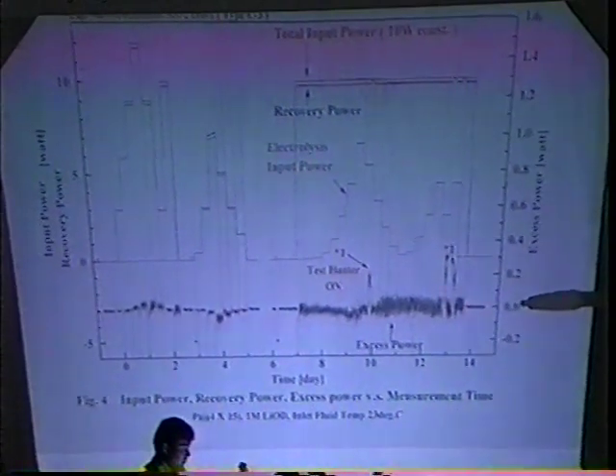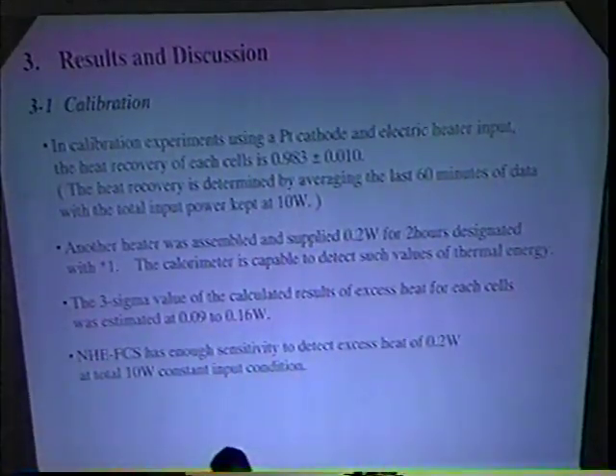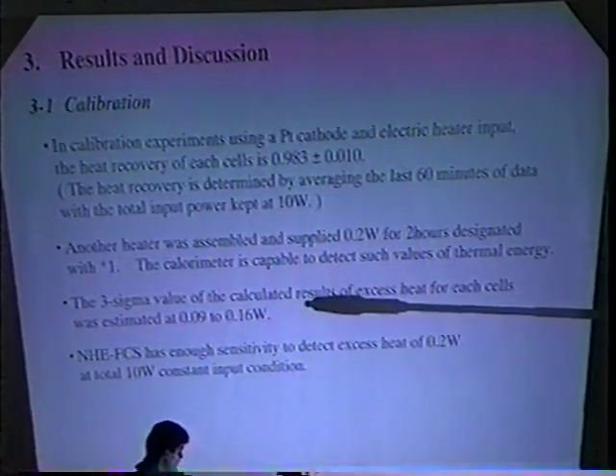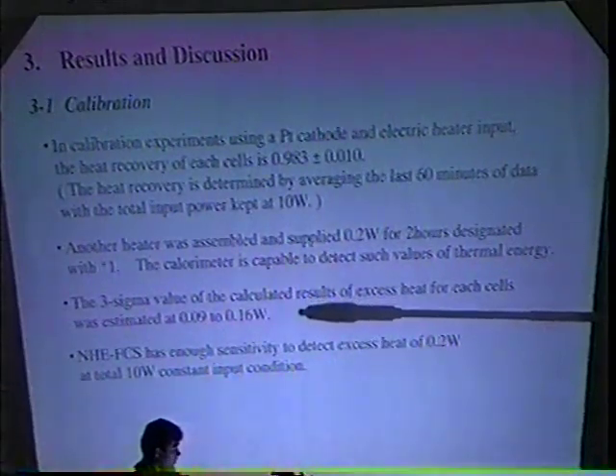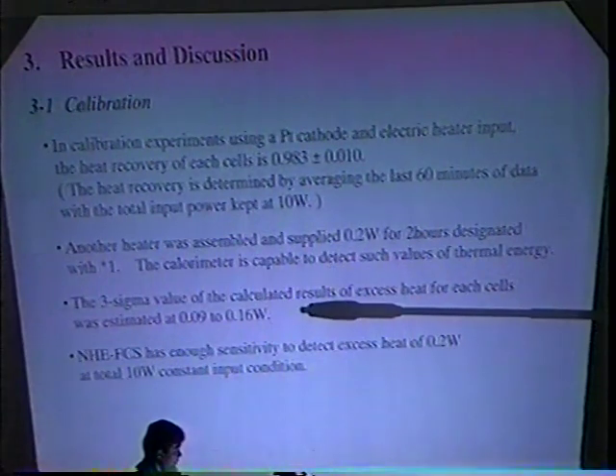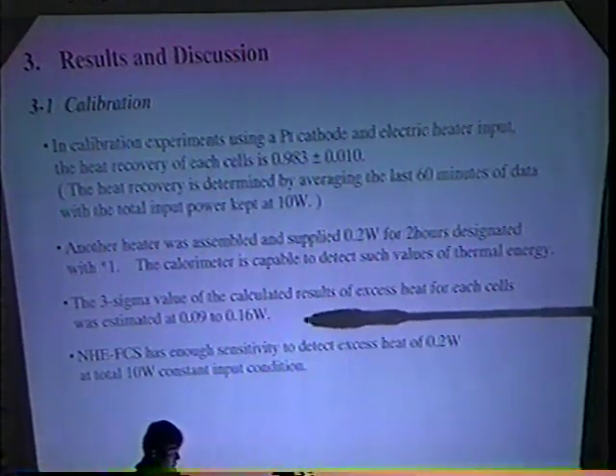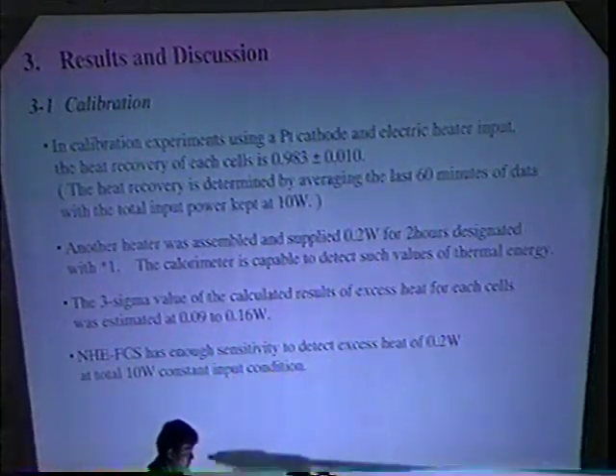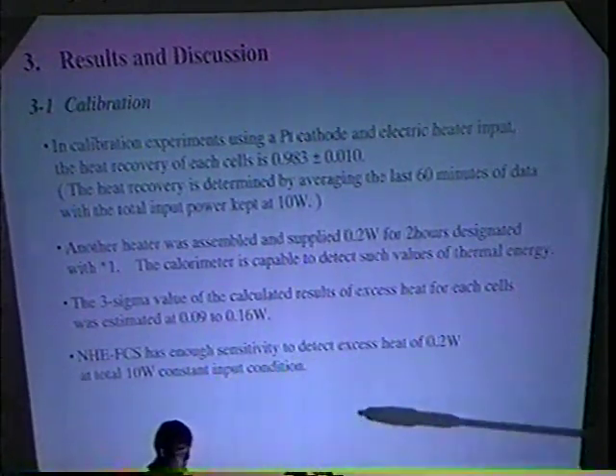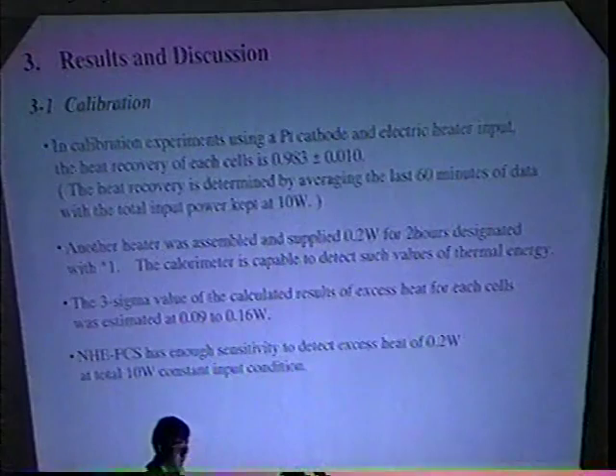In this figure, the calculated result of excess heat is almost plus minus 0.1 watt, except during the period when the test heater was on. The 3 sigma values of the calculated result of excess heat for each cell were estimated at 0.09 to 0.16 watt. So NHE-FCS has enough sensitivity to detect excess heat of 0.2 watt at a total 10 watt constant condition.